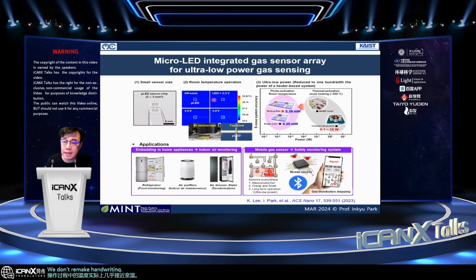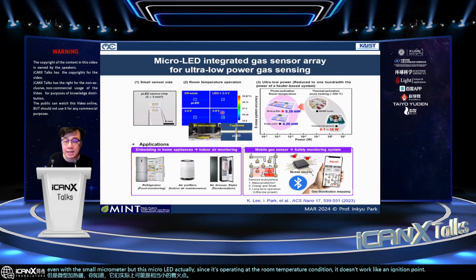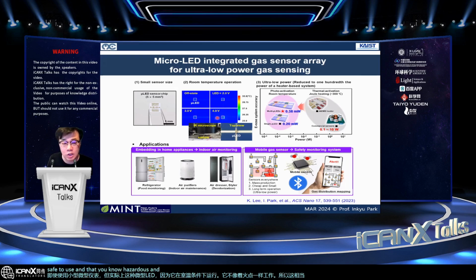We don't generate heat by the micro LED, we actually just activate the material with the light energy. The temperature rise is actually lower than 5 degrees Celsius compared to the room temperature condition. And that is quite useful for applications where we need to worry about flammable or explosive gases like hydrogen or methane. Because by using a microheater, there could be quite a small ignition point even with the small microheater. But this micro LED, since it's operating at room temperature, doesn't work like an ignition point. So that's quite safe to use in those hazardous and flammable situations.